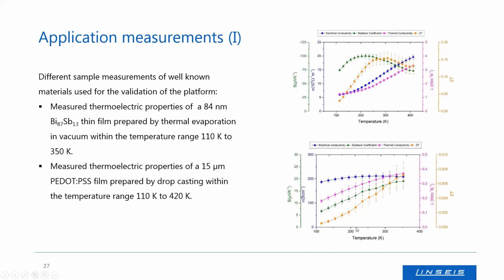The lower picture shows the result for a thermoelectric polymer film, an organic material with a low thermal conductivity, PEDOT:PSS. The film was prepared by the drop casting method. And as we saw previously, for materials with low thermal conductivity, you need thicker samples. In this case, the film had a thickness of 15 micrometers. Once more, you find thermal conductivity over temperature. You find electrical conductivity, the Seebeck coefficient, and from these parameters, you can calculate the figure of merit, shown in yellow.